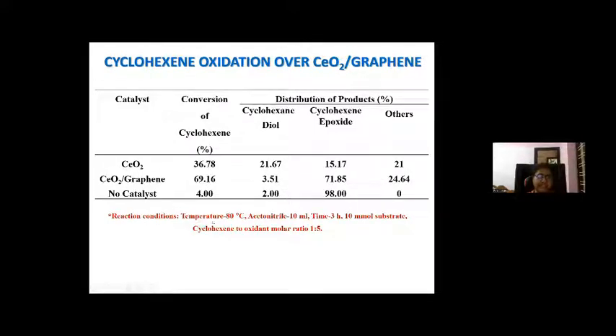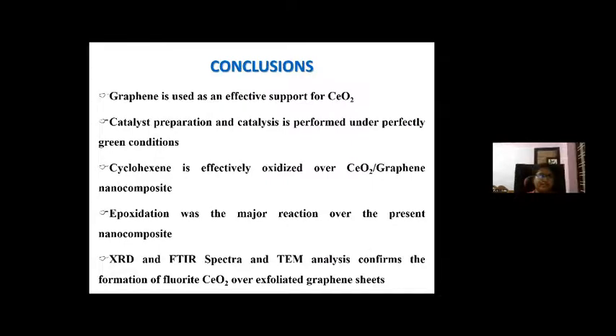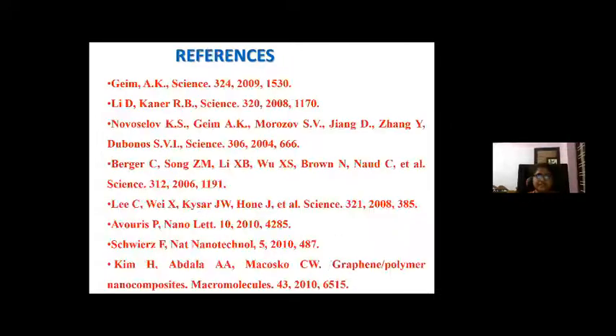The reaction conditions are a temperature of 80 degrees Celsius, the solvent is acetonitrile, for a 3-hour reaction using 10 millimole substrate, and the cyclohexene to oxidant molar ratio is 1:5. The major product is cyclohexene epoxide, and conversion is 69%. So the major conclusions are: graphene is used as an effective support for ceria for enhanced catalytic performance, and the catalyst preparation and catalytic reaction are performed under perfectly green conditions. Cyclohexene is effectively oxidized over the graphene nanocomposite, and epoxidation was the major reaction. The material characterization confirms the formation of fluorite ceria over exfoliated graphene sheets. These are some of the references.